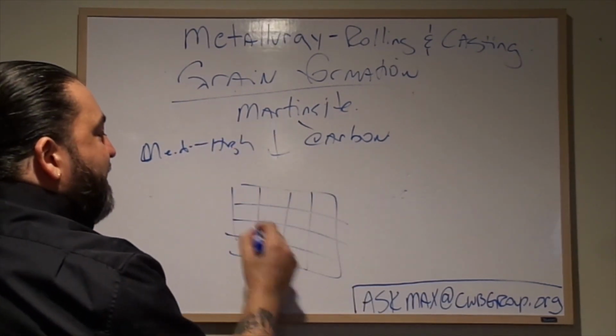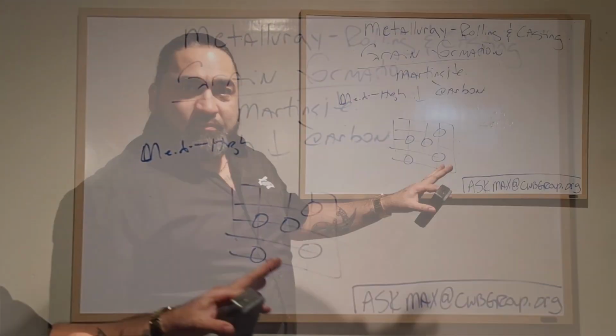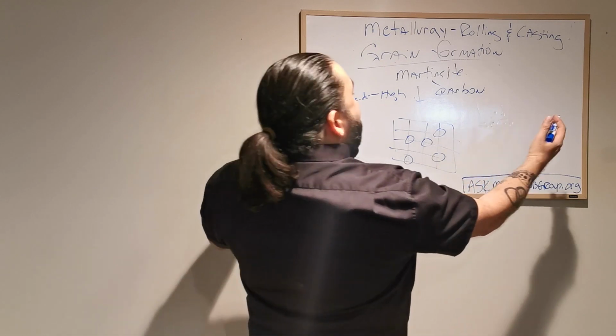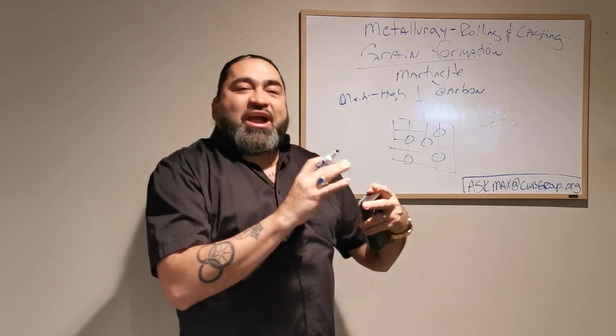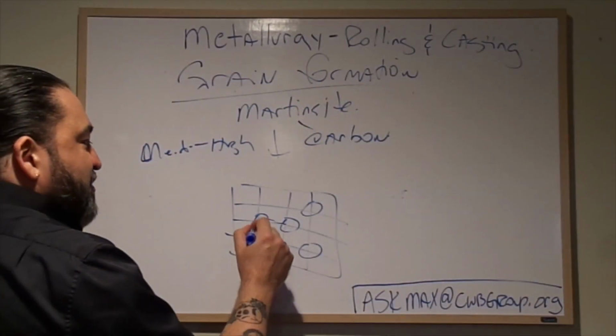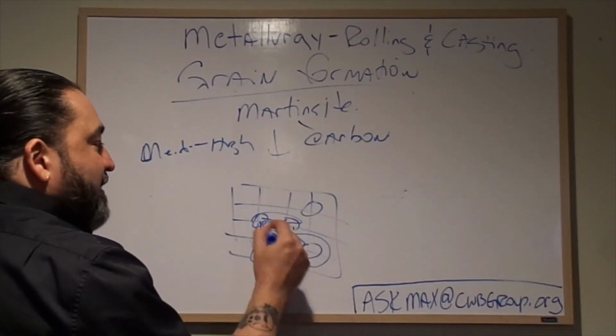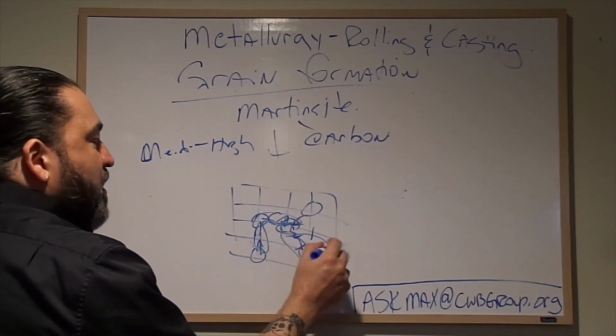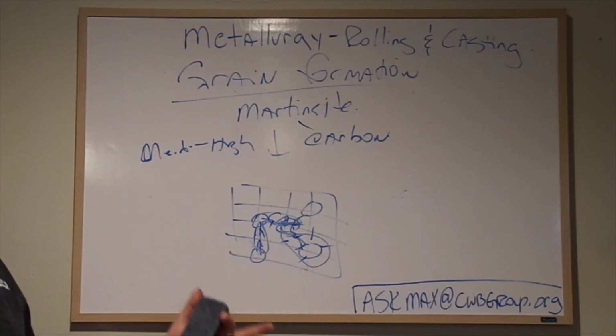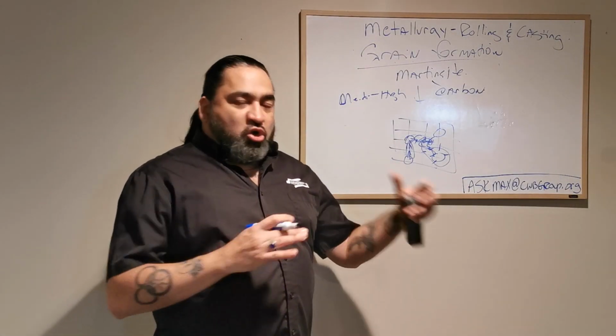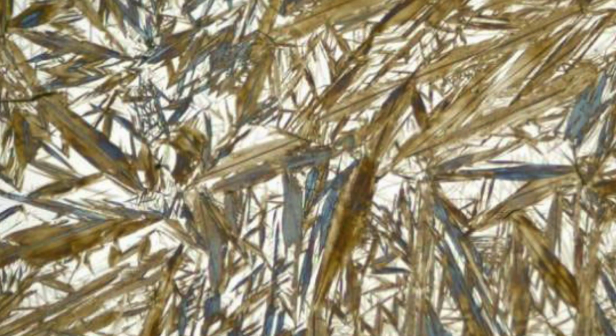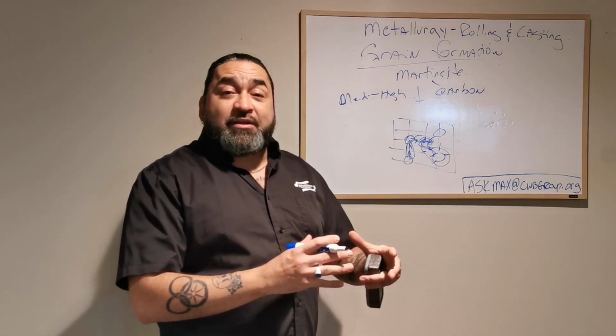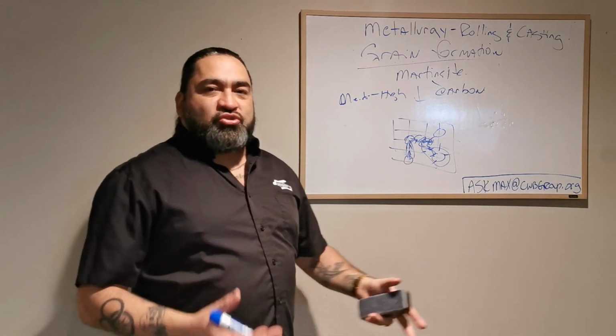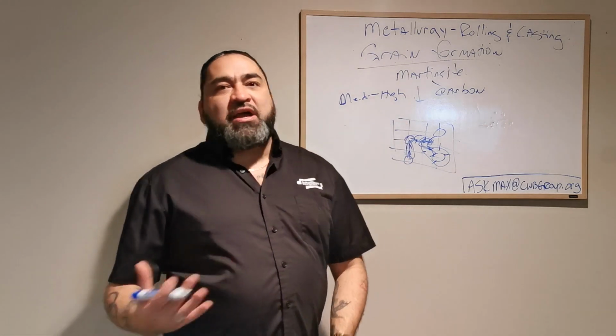Where I have enough carbons floating around that when this gets quenched, the quick contraction of the material actually smashes some of these together, and they will then collect and create a carbon deposit that will then disrupt the lattice. Now, that martensitic growth means that it's carbon caught in pools together that were not evenly dispersed because they weren't allowed the time to do that, which would have happened normally in a slow cooling process. In the quenching process, they were captured and stuck. And now that will cause carbon issues such as martensite. Now, that's only on medium to high carbon steels.